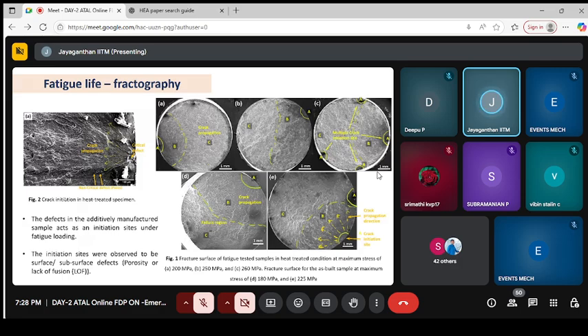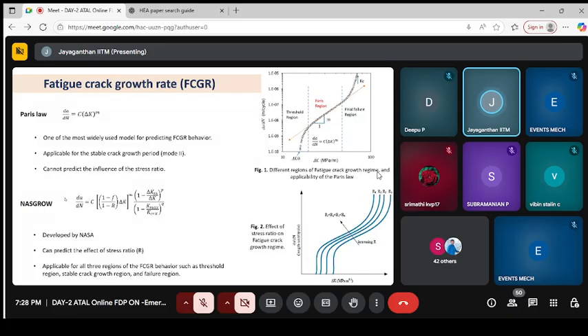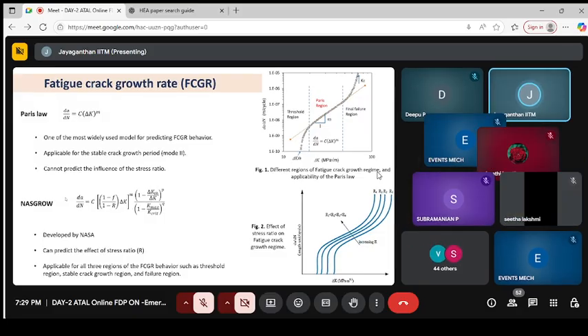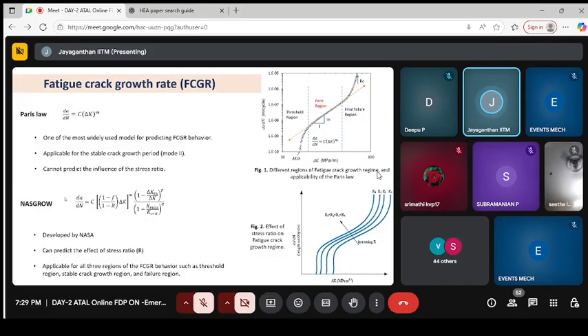We have never accounted inherently for the presence of internal cracks. The moment you have a crack inside the sample, as I mentioned, it might have pores or cracks inside the material, for which you need to understand the role of cracks or flaws present in the material. That's where we need to do fatigue crack growth studies, for which you can make use of a CT sample, compact tension sample. Again, by using a UTM machine, you can apply the load. We continuously track the growth of the crack, how it moves across the cross section of the sample.